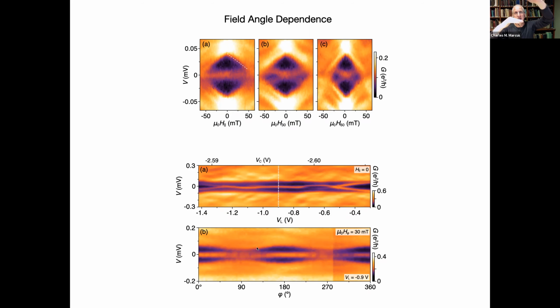Now the gap is smaller. The gap is not the full superconducting gap. It's reduced, as you saw from those peaks, probably because of a combination of the Zeeman or this exchange field plus some combination of spin flip and spin orbit scattering that we don't yet know or understand. But it still needs a Tesla scale field to bring those levels down to zero. In fact, you can see that they're not really adequately being brought down to zero all the time, because sometimes it's not enough to bring them all the way to zero and they seem to split. That's what's going on here. But the field that's swinging around, that's doing this magnetization, is only 30 millitesla. So all it's really doing is dragging the domains around with it.